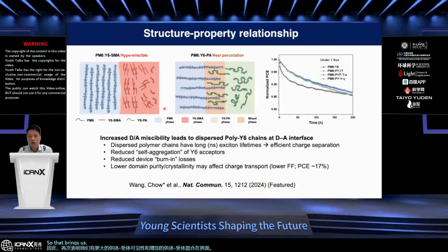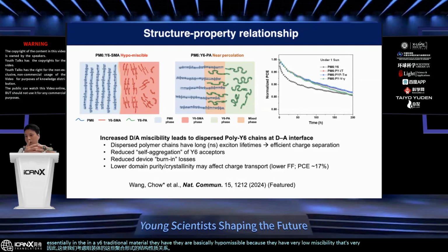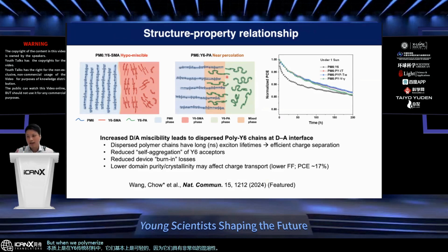So that brings us to consider the structure-property relationship of these polymerized versions of the acceptors. Essentially, in the Y6 traditional material, they are basically hypomiscible because they have very low miscibility. There's almost no mixing at the interface. But when we polymerize them, there's increased miscibility, which enables us to form this donor-acceptor percolation network at the interface.